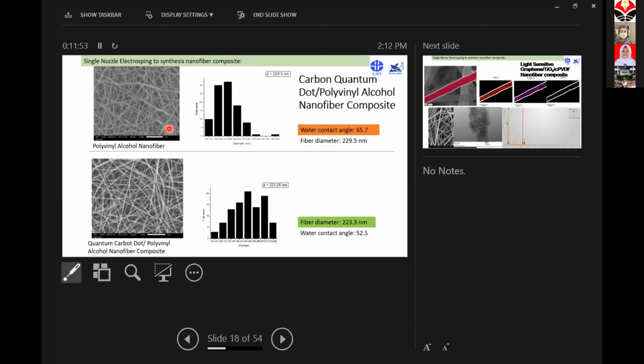For the composite, in the optimum condition, we can get the smooth quantum carbon dot PVA nanofiber composite with diameter around 223 nanometers. What happened on the surface? You can see here the water contact angle of the PVA. PVA is a hydrophilic polymer, and the water contact angle is around 65. When we add quantum carbon dots, the water contact angle is around 52. It means we can make a more hydrophilic nanofiber composite, quantum carbon dot polyvinyl alcohol nanofiber composite.